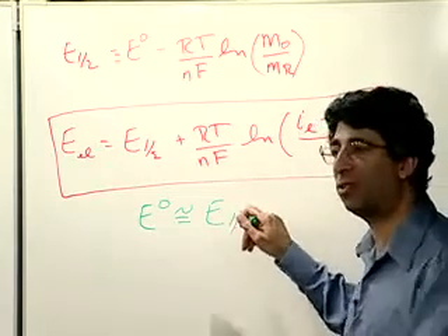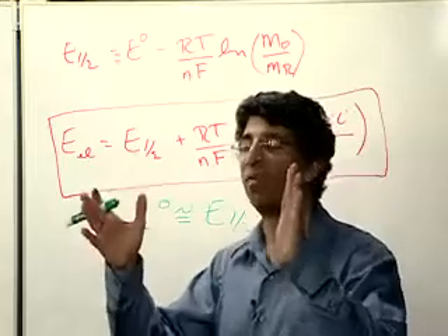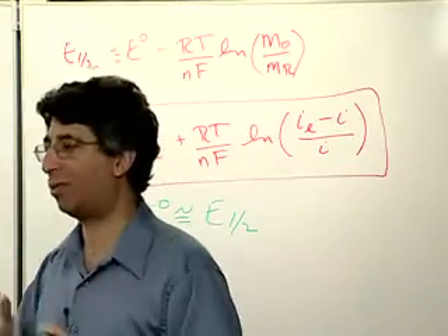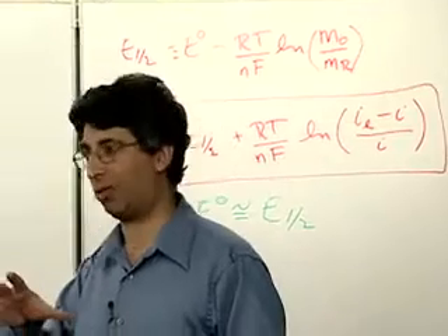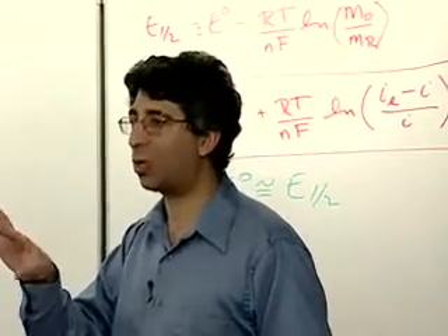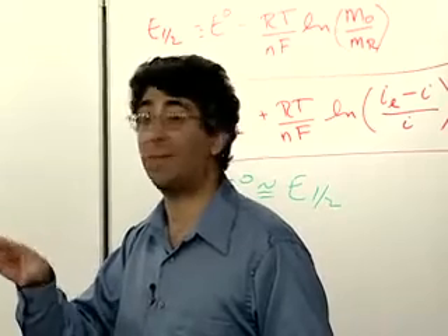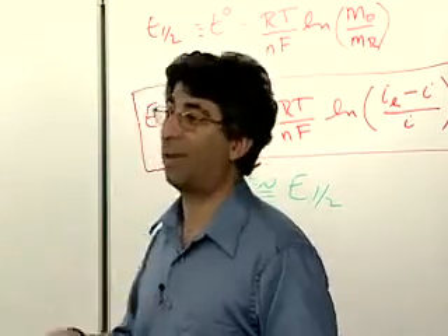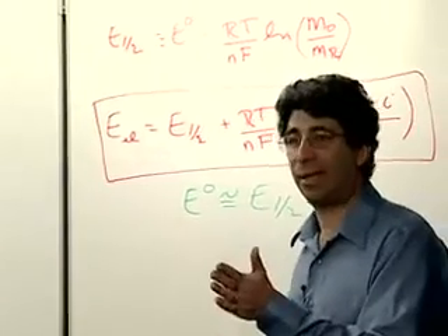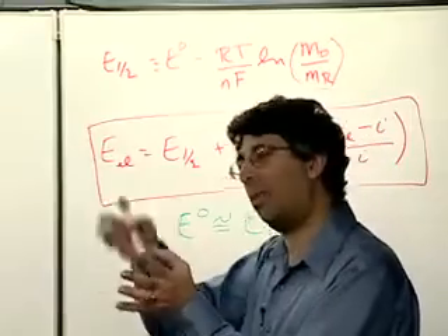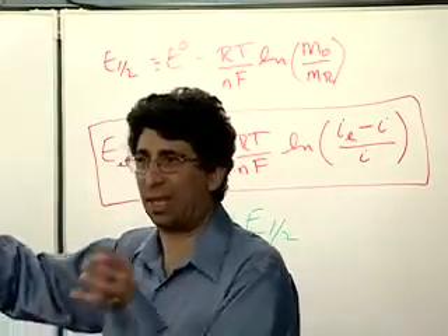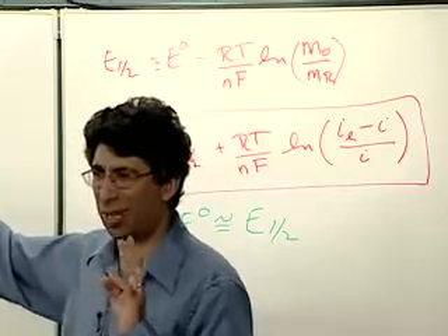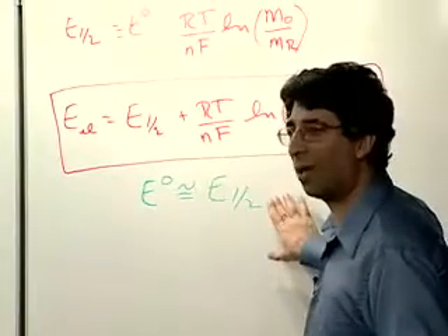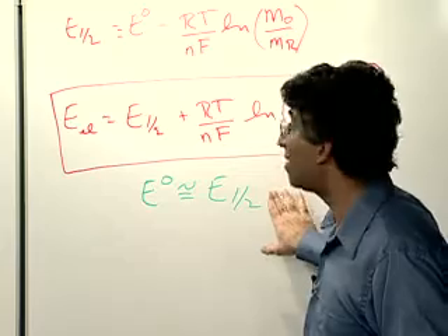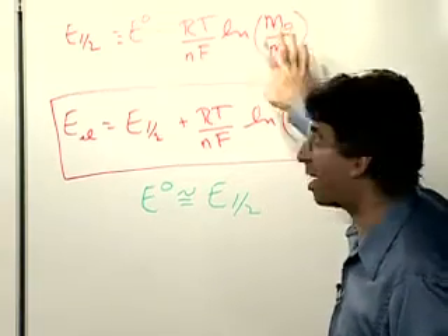So we have to look at that certainly, because the assumption is that is not happening at all here. Now, staying with that diffusion just for 1 second, let me finish that one thought I had. To give you a comparison, if I'm thinking about a molecule diffusing at room temperature through a solid state matrix, the sort of numbers I'm going to come up with are on the order of 10 to the minus 10 centimeters squared per second. So you can see in solution, if you pick one molecule versus another, it might be 2 times 10 to the minus 5 centimeters squared per second, and the second molecule might be 10 to the minus 6 centimeters squared per second, or something like that. But that is such a small difference compared to what you would have, say, in the solid state for diffusion, that we can consider both these sorts of numbers about the same and not affect this dramatically.